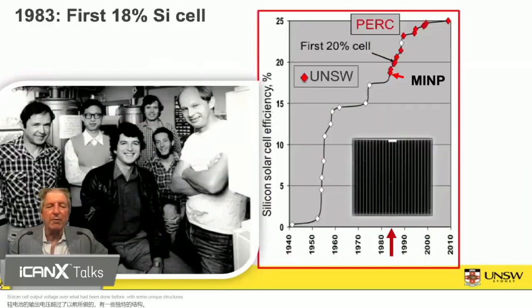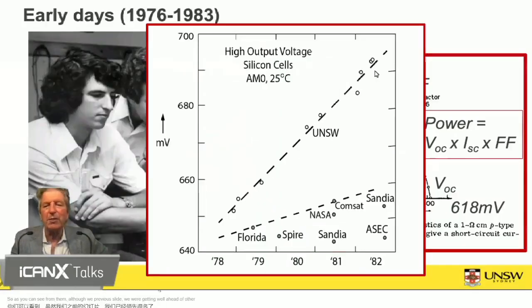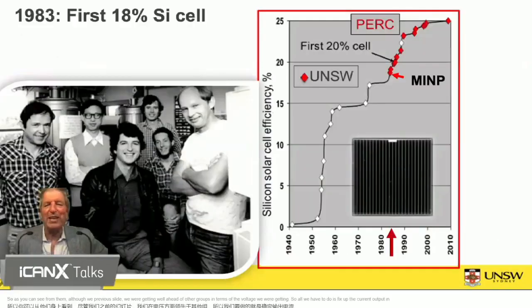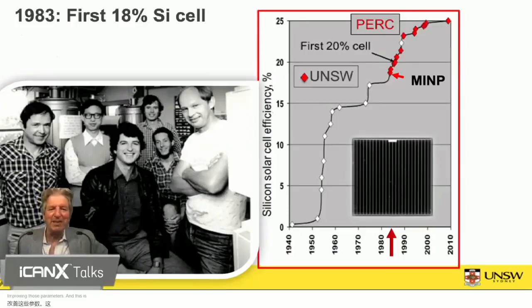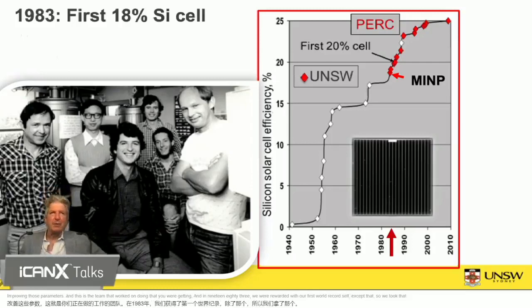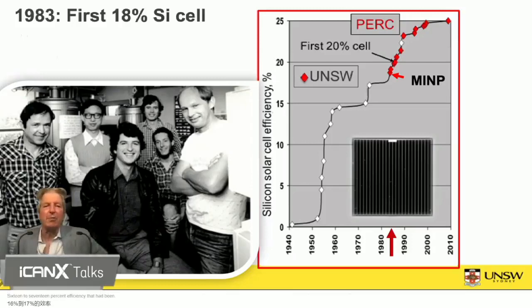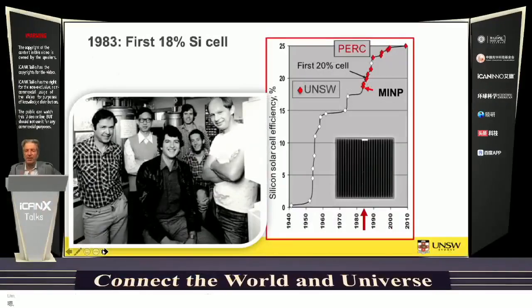So as you can see from the previous slide, we were getting well ahead of other groups in terms of the voltage we were getting. So all we have to do is fix up the current output and the fill factor, and we could get a decent cell. So we put a lot of effort into improving those parameters, and this is the team that worked on doing that. And in 1983, we were rewarded with our first world record cell. So we took the 16 to 17% efficiency that had been demonstrated at ComSat laboratories up to 18% with the cell that you can see in the photo to the right.